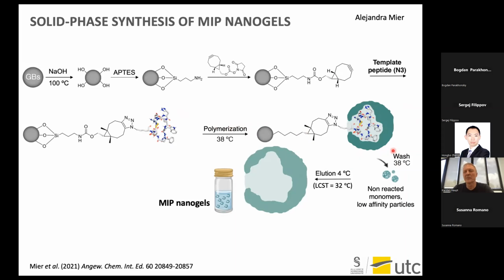Now, since we have a recipe with a large content of NIPAM, we will end up with polyNIPAM, and polyNIPAM really has thermoresponsiveness also in our case here. And the transition temperature, the LCST or lower critical solution temperature, is about 32 degrees. And we will do the polymerization above the LCST, where the polymer is compact, as you see here. So the polymer is compact above the LCST.